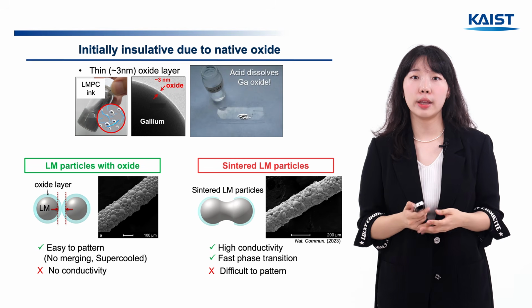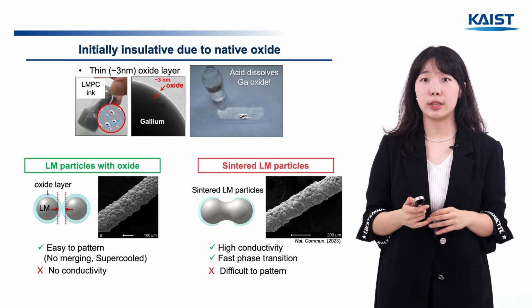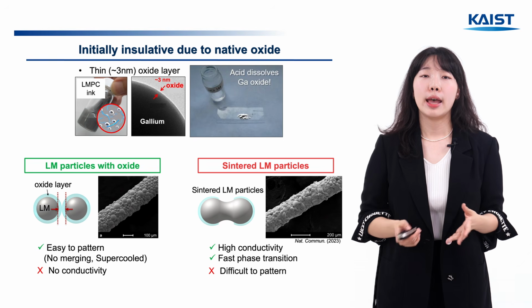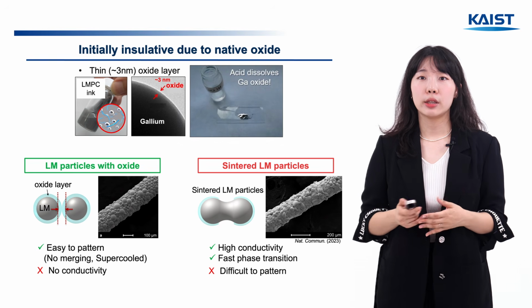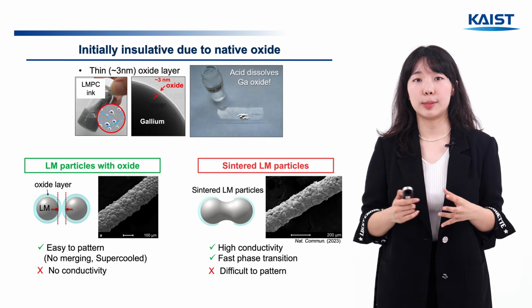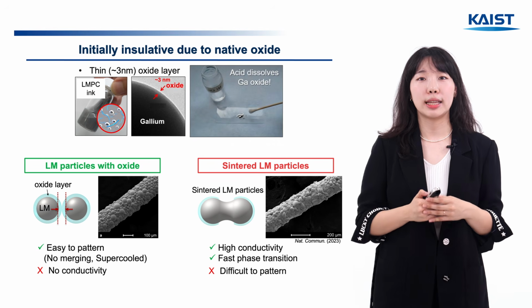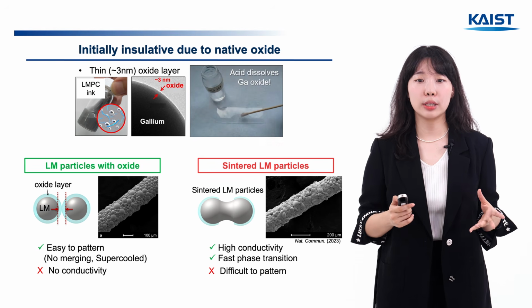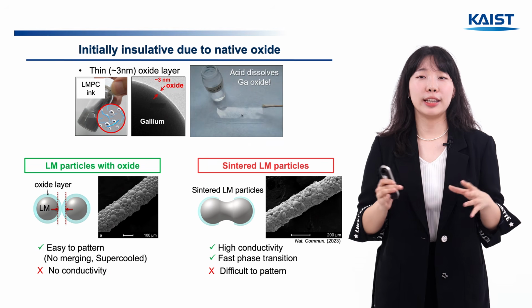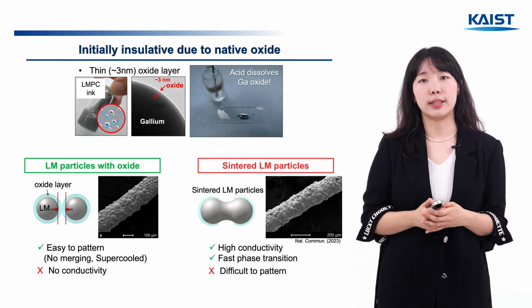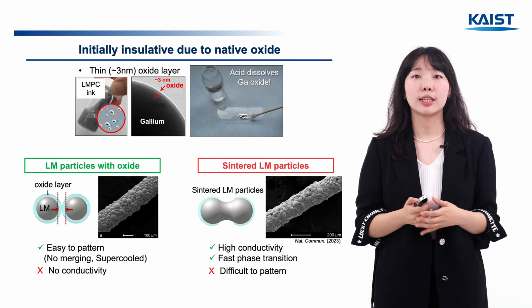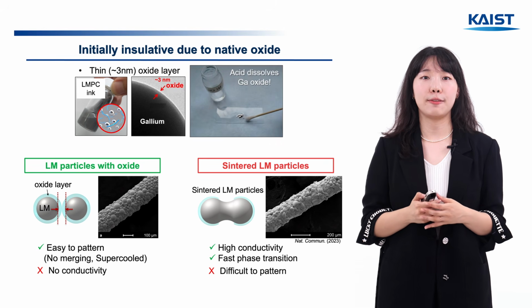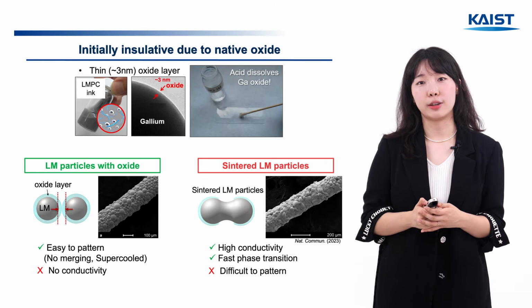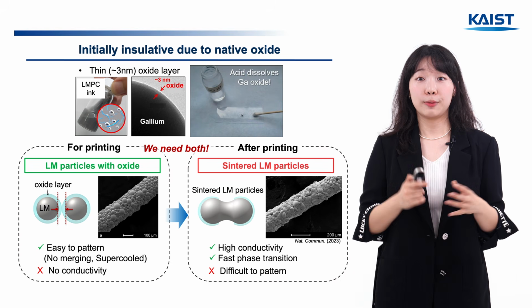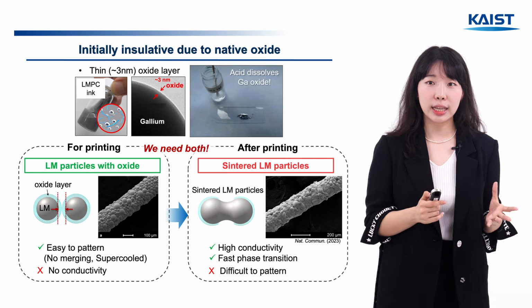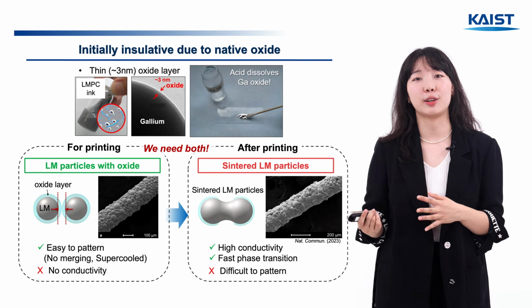Each gallium particle in the LMPC ink is covered with a 3 nanometer oxide layer. As you can see in the video on the right, the gallium oxide layer dissolves when exposed to acid. With the oxide layer, the particles stay dispersed, so the patterning is very easy, but there is no conductivity. Without the oxide, the sintered particles are conductive and freeze quickly, but it cannot be patterned. So, for the patterning, we need the former state, and after patterning, we need the latter, sintered state.